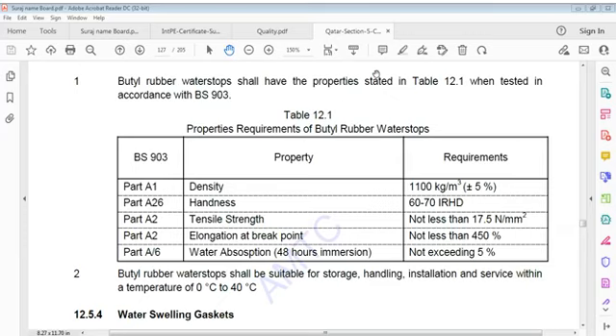Then Part A2, tensile strength, not less than 17.5 Newton per square millimeter. Then Part A2, elongation at break point, not less than 450%. We're talking of butyl rubber, mind it. And Part A6, water absorption, 48 hours immersion, not exceeding 5%. Butyl rubber water stops shall be suitable for storage, handling, installation and service within a temperature range of 0 to 40 degrees Celsius.